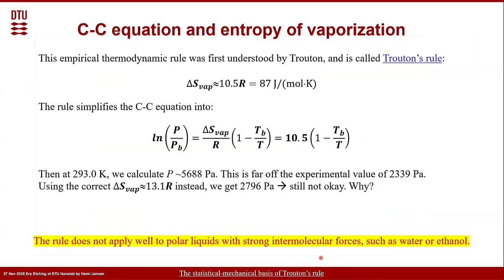So now this empirical formula of 87 joules per mole Kelvin was first understood by Trouton. It's called Trouton's rule. So it means that the entropy of vaporization is 87 joules per mole Kelvin. Taking this, now our rule of the Clausius-Clapeyron equation really makes everything very easy, because the natural logarithm of the vapor pressure we want to know divided by the boiling pressure is 10.5. We just follow the numbers, because in fact 87 joules per mole Kelvin is 10.5 times the gas constant. So we get 10.5 times 1 minus the boiling temperature divided by the temperature we want to know the vapor pressure.